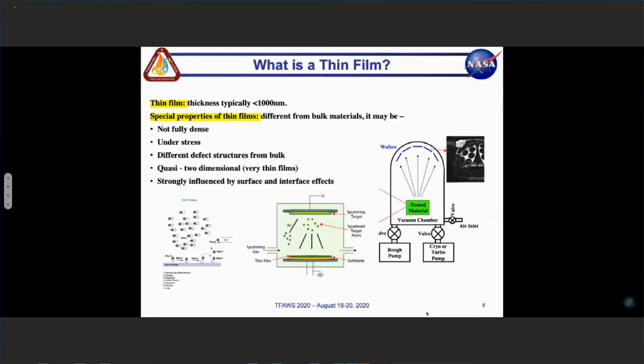The middle thin film process is your sputtering process, where the top green is your sputtering target. You hit that with a high energy argon source, which creates a bombardment of your target. It's this sputtered, pulverized target material, which is all over your vacuum chamber, that then reacts with your substrate. And again, thickness is controlled by how long you continuously bombard the target with that argon source or that high energy source.